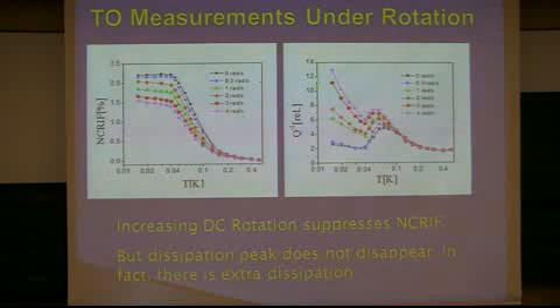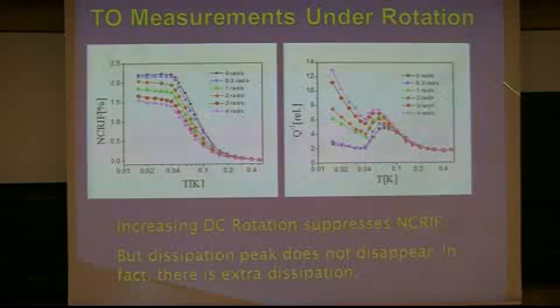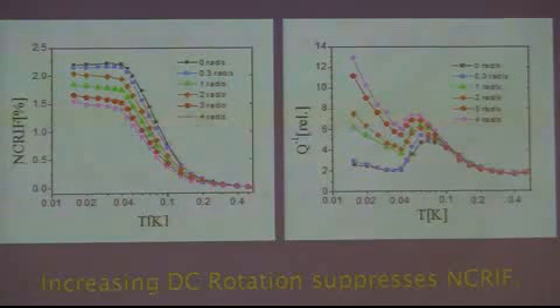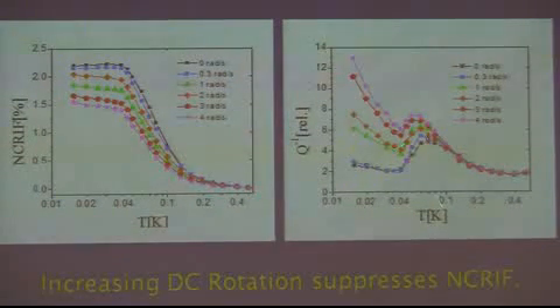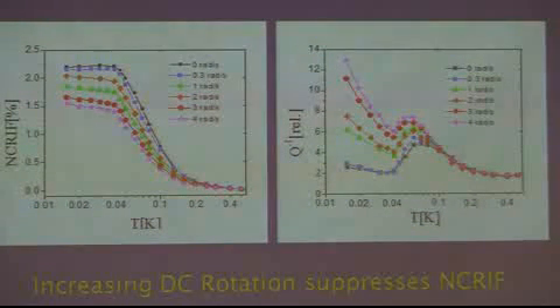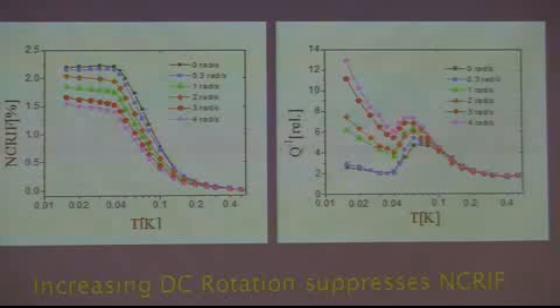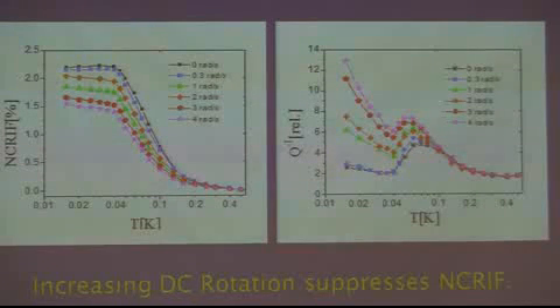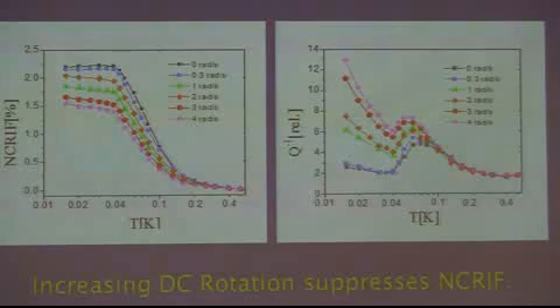And this is the energy dissipation as a function of temperature. The reason I show you this is that the effect of rotation on the dissipation is very different from the AC case. As I told you, if you increase the AC oscillation, you can suppress the non-classical rotational inertia, and at the same time the dissipation as well. However, here it is the opposite. If you increase the DC rotation, then you increase energy dissipation as well. We don't completely understand the reason for this. However, this is probably related to the injected quantized vortices interplaying with some residual vortices in our solid helium. Maybe not.